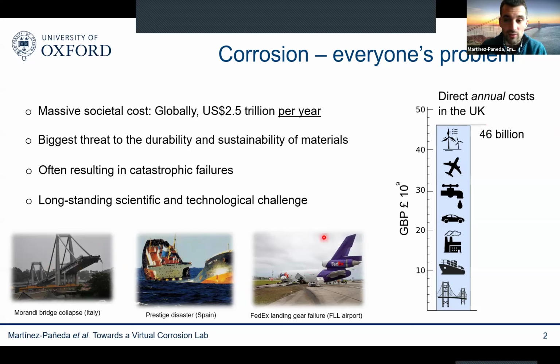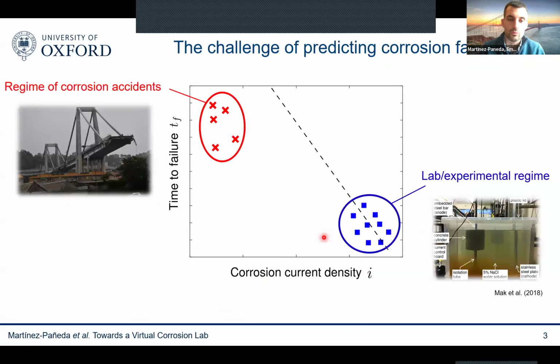We have learned a lot, of course, through decades of experimental corrosion science, but we have not been able to incorporate that insight into a model. So it's a problem that has eluded, in particular, computational scientists. And as a result of that, we lack predictive models. And as a result of that, we are seeing these catastrophic failures occurring more frequently every day, across the entire world, in well-developed countries with well-established engineering standards. There are multiple reasons why we are still unable to predict corrosion failures despite decades of research into this area. I think one of the reasons is that often the conditions under which we run our experiments are very different to the conditions under which these catastrophic failures happen.